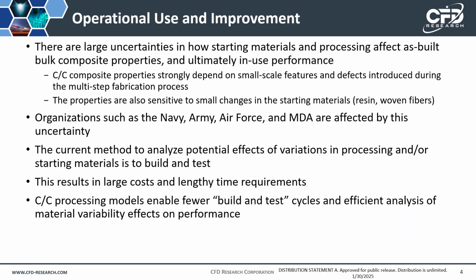The application for Navy operational use and improvement arises directly from the multiple sources of variability and uncertainties in the composite production. The properties of the final composite depend on small-scale features. For example, unfilled pores or cracks in the carbon matrix and their location relative to the fiber reinforcement, in addition to any larger-scale defects such as a portion of the component that resin did not reach during infiltration. The starting materials are complex reinforcements woven from thousands of individual fibers and polymer resins with a distribution of molecular weights and reactive chemical groups. Given all of these sources of potential variability in the as-built composite, models capable of predicting which characteristics of the key inputs must be tightly controlled and how sensitive the composite properties are to process variables can enable fewer of the slow build and test cycles to speed production of quality components.